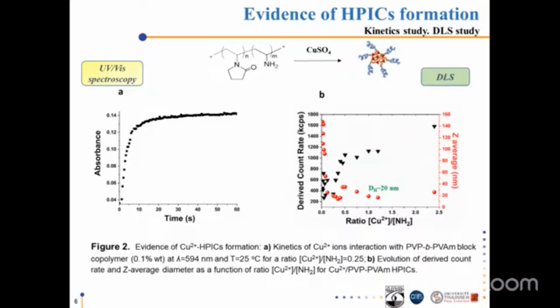In the absence of copper ions, the polymer forms polydisperse and large aggregates appear due to HPICs formation. The diameter of these aggregates at the ratio 1 to 4 is about 20 nanometers.